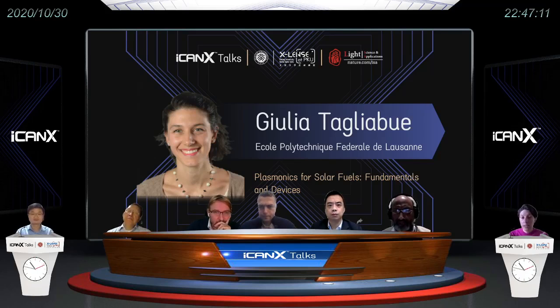And this remains a big open question in the field, compared to the high extraction efficiencies that we see from the ultra-fast spectroscopy experiments. In our measurement, we estimate 90%. Measurements on the hot electron side estimate 50%, but no steady state device has been able to approach these values. So this is a major challenge to be clarified.